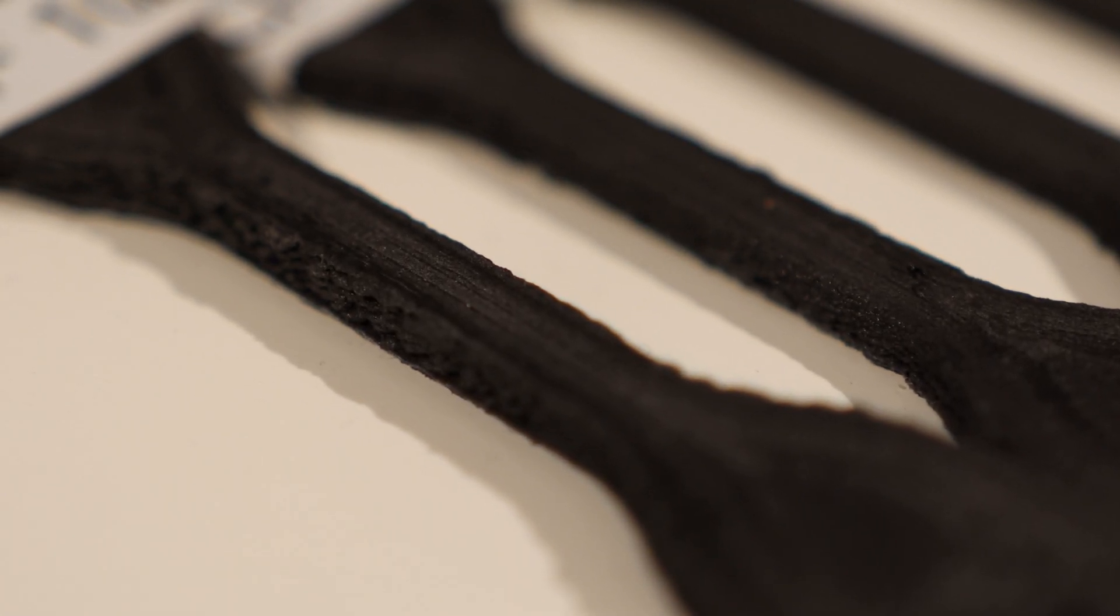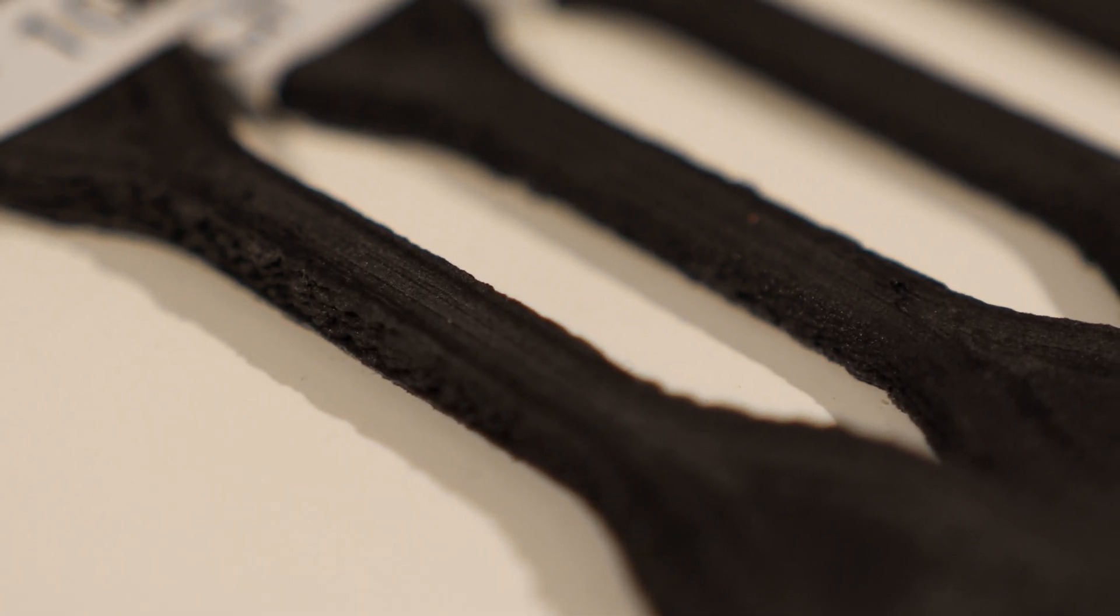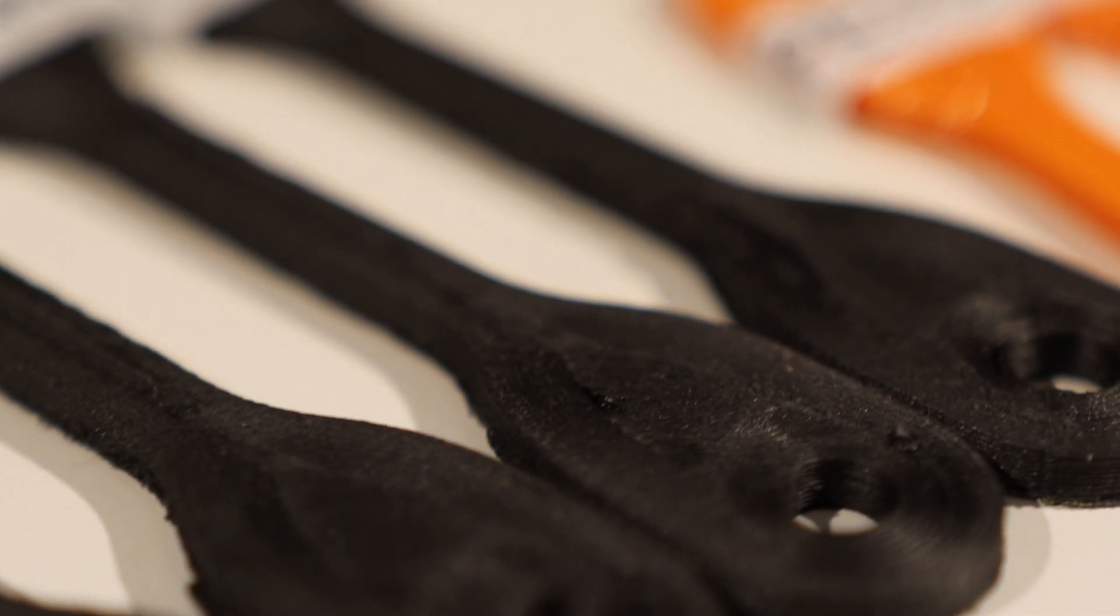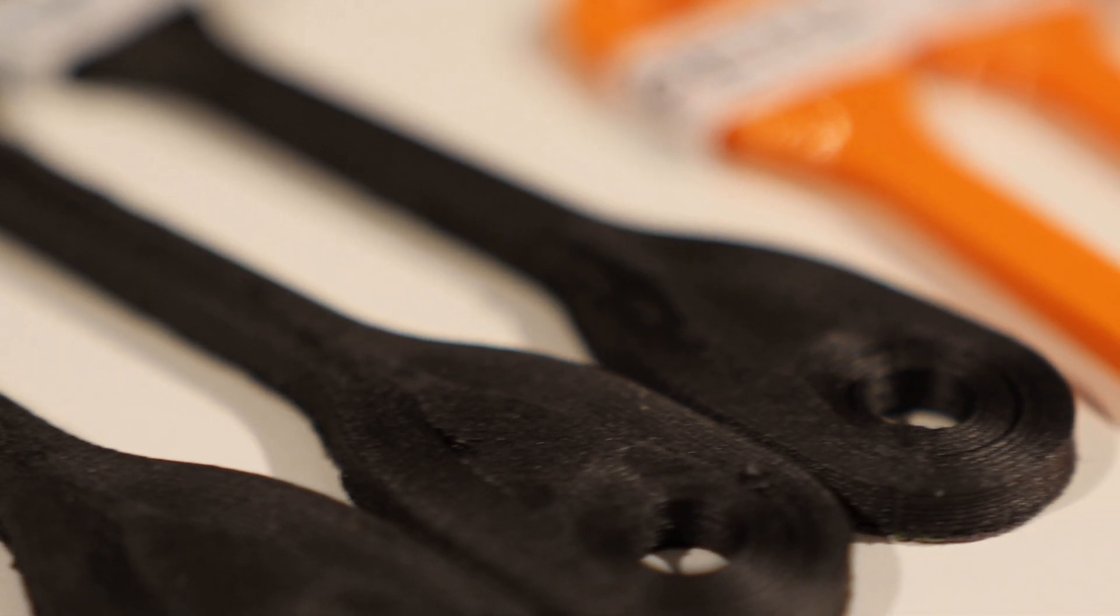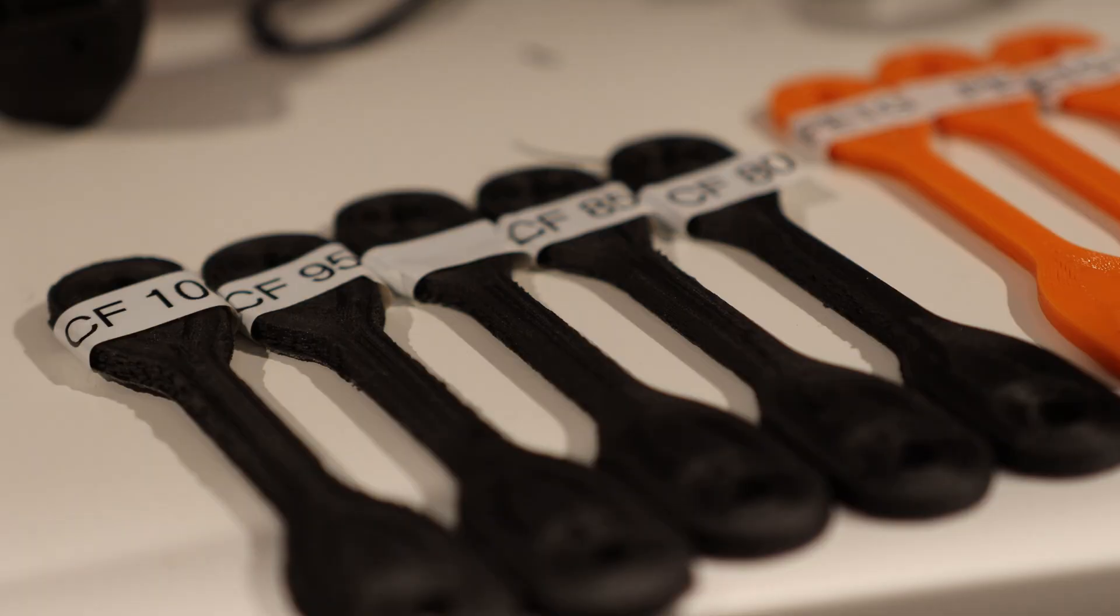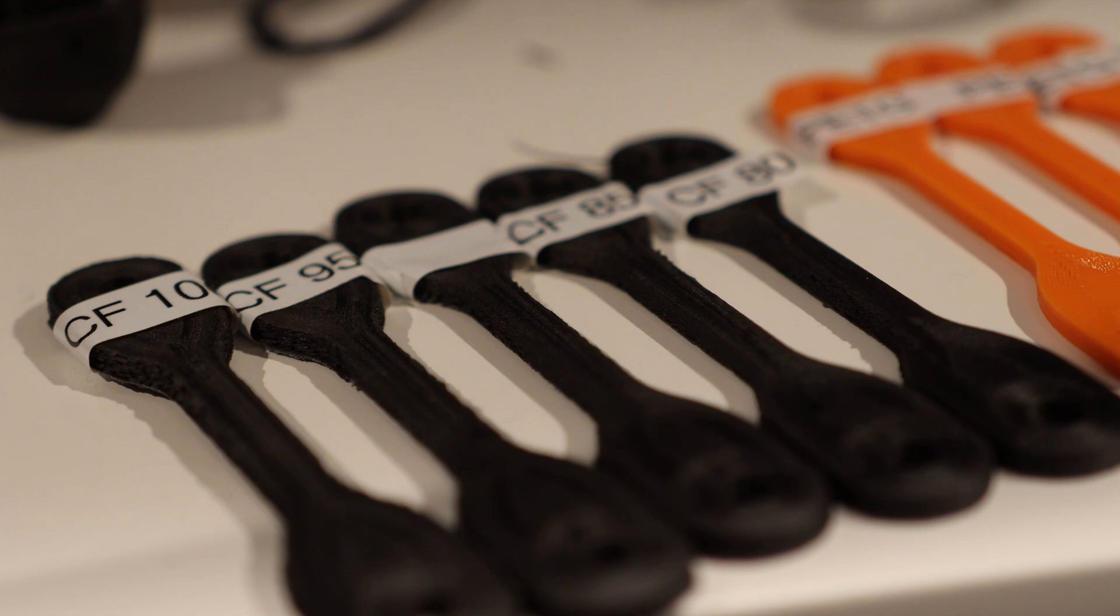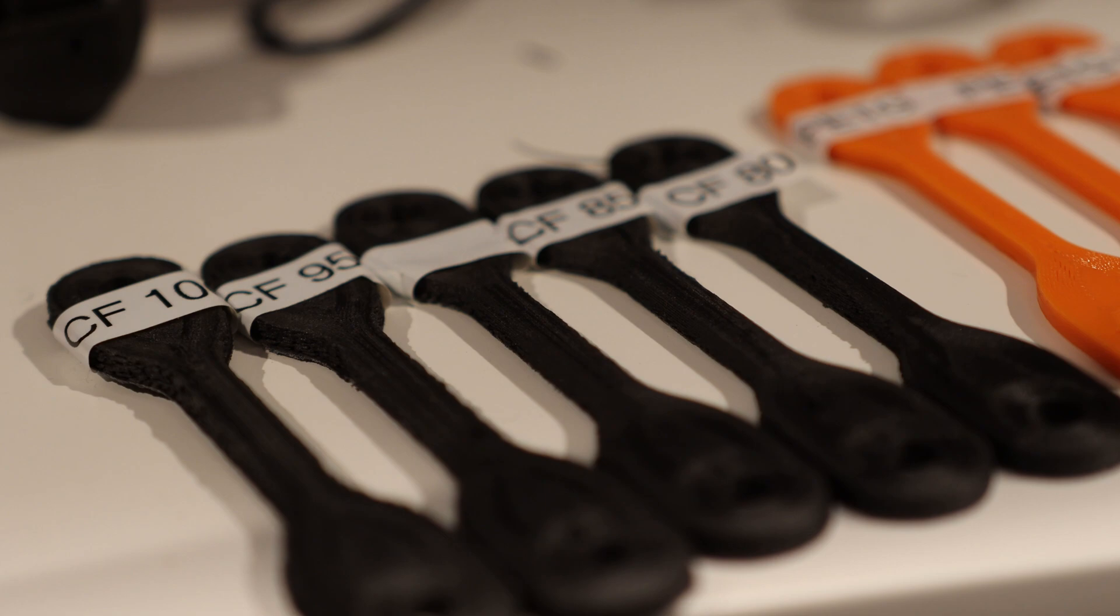If we look at my carbon fiber specimens, you'll notice that there's a little bit of overextrusion on all of them. I'm pretty sure this overextrusion was caused by the filament being wet. As it passes through the nozzle and is heated up, it goes past the boiling point of water. So any moisture that's trapped in the filament instantly converts to steam and puffs it up like popcorn.